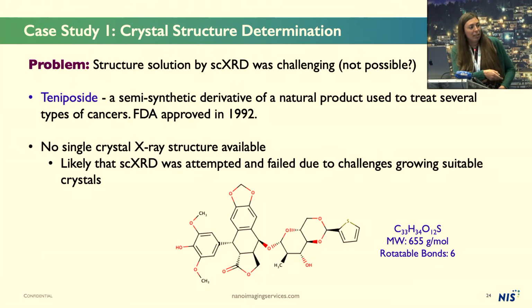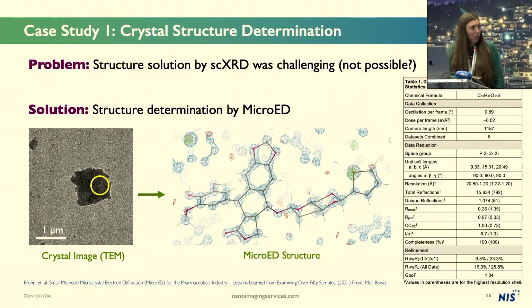As you can see, the molecular weight is a little bit high. We're, again, violating Lipinski's rule of 5 here. And there are 6 rotatable bonds. It's not quite as complex as some of the molecules we've seen, but up there. So we purchased this compound from a vendor and put the direct powder from the vendor onto a grid. We found these rather ugly looking particles. The surfaces are not the cleanest, but we were able to get diffraction data from these and determine a microED structure from this sample.